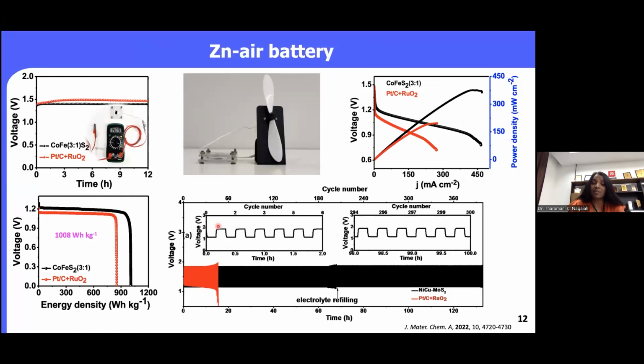So we have assembled the zinc air battery in this case. And to understand this, we have monitored the OCP, that means open circuit potential. And for a comparison, we have taken the platinum carbon as well as the ruthenium oxide, which is very important as a standard catalyst. And as you can see, the potential is almost stable even for 12 hours. There is a small decay in the case of the state of the art catalyst. So now we have connected here.